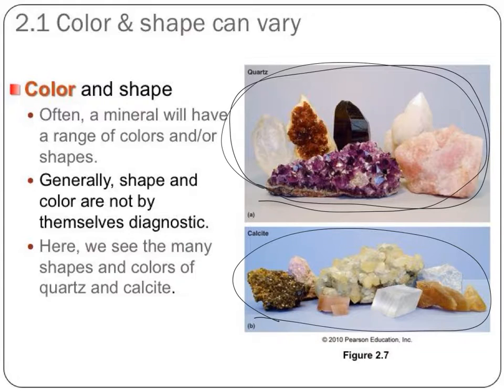Impurities. One way to say it would be impurities, but the different kinds of trace elements, trace cations that are built into the matrix will determine whether you have this kind of clear-ish quartz, more comparable to what you think of as quartz, or this milky quartz. The milky quartz also, I think, has some issues with small air spaces that have been incorporated into the quartz matrix, and that scatters the light in such a way that it gives it that milky appearance.